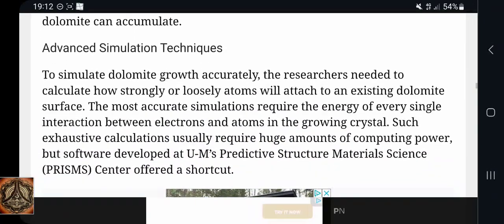Luckily, these defects aren't locked in place because the disordered atoms are less stable than atoms in correct positions. They are the first to dissolve when the mineral is washed with water, repeatedly rinsing away these defects, for example with rain or tidal cycles, allowing a dolomite layer to form in only a matter of years. Over geologic time, mountains of dolomite can accumulate.